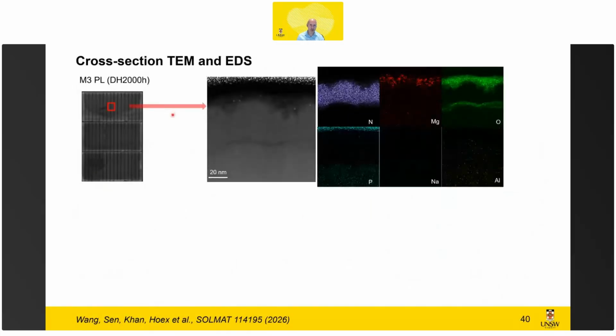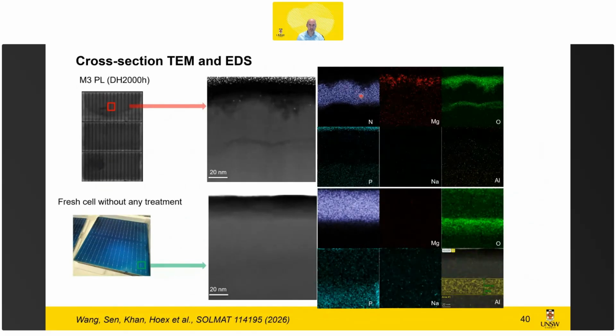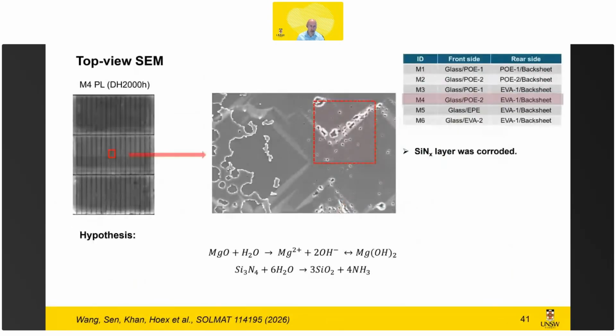But then if we looked at cross-sectional TEM, we identified that this magnesium had resulted in a very strong reaction with the silicon nitride layer. At the end, we came to the conclusion that the magnesium oxide in combination with water actually fully corroded the silicon nitride. And this reaction triggered a degradation of the TOPCon contact. It's still a bit confusing why something happening at the surface can wreak havoc at a polysilicon oxide contact buried at 100 nanometers. But we believe it's probably due to the release of hydrogen as part of this reaction chain. So with ammonia, there could be alternative pathways that release a lot of hydrogen, or the fact that stress is formed. But details can be found in the paper.